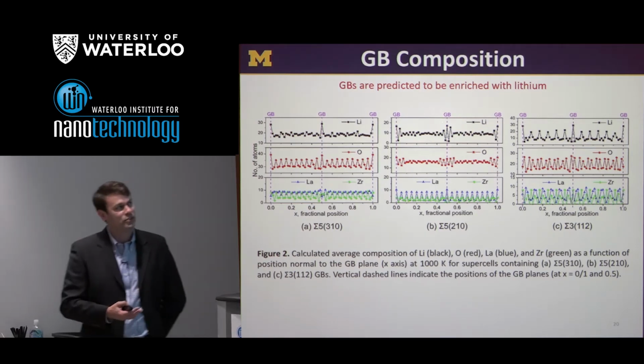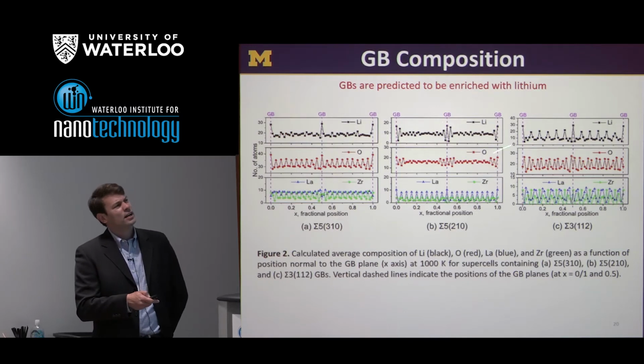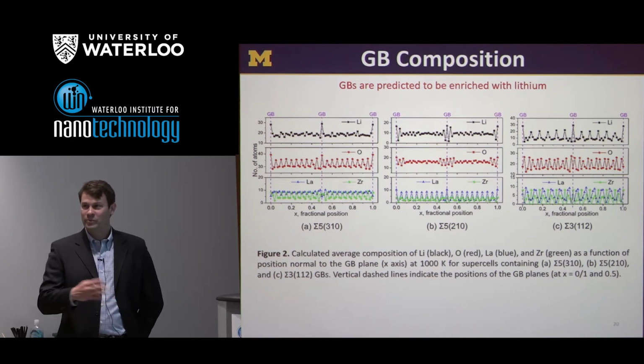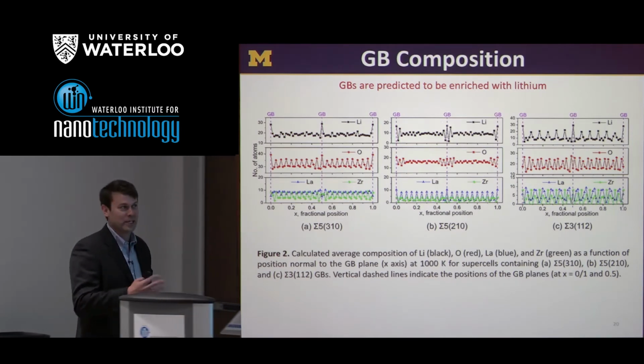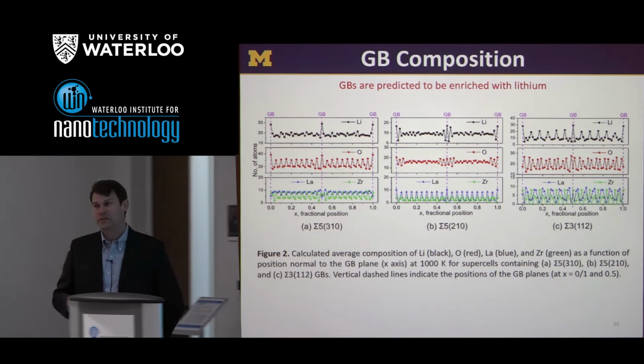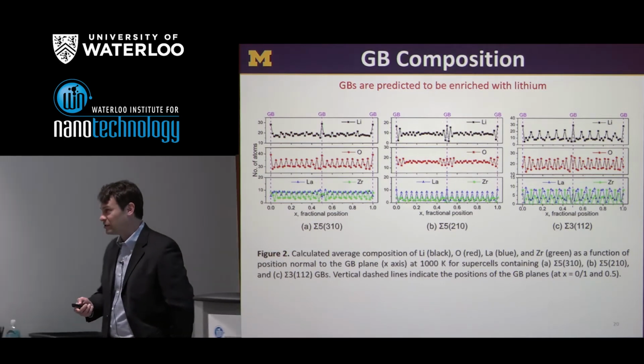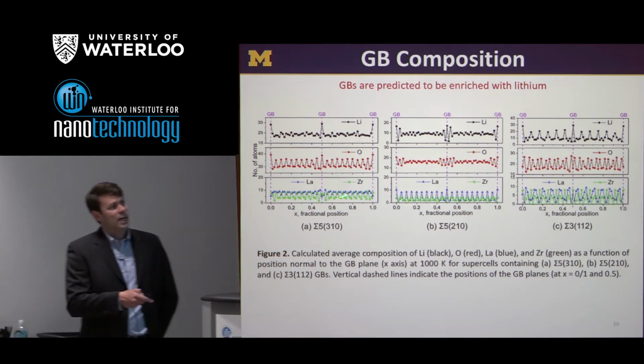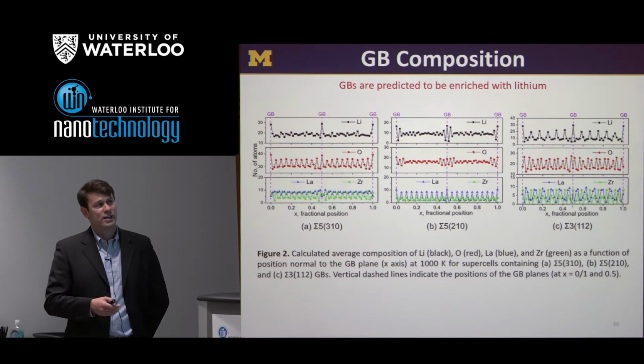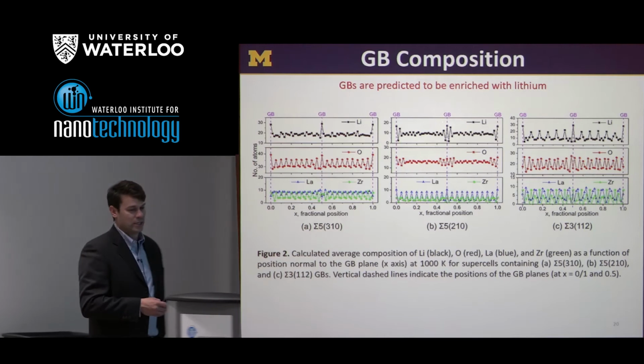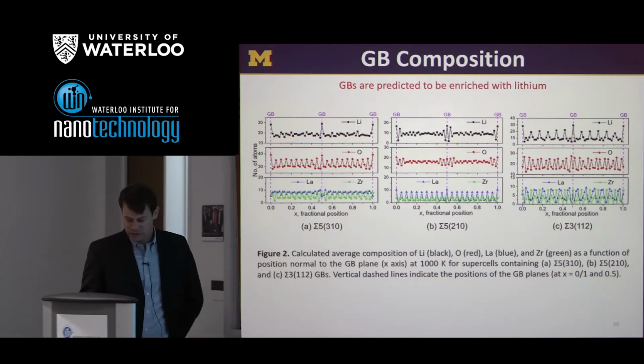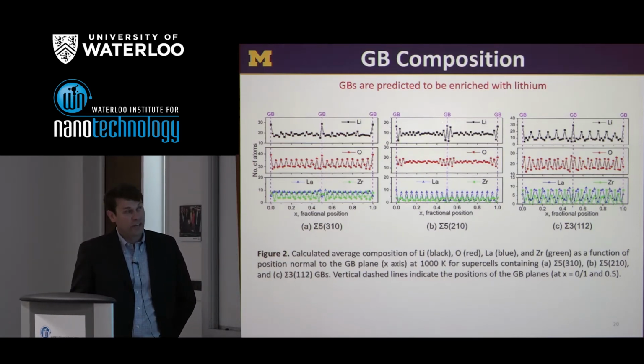So there's some enrichment of lithium occurring here, which also coincides with a somewhat weaker enrichment of oxygen. So perhaps there's some electroneutrality constraint here that we can't overload the grain boundary with positive lithium, but there has to be some anion present to balance that charge. But then for lanthanum, zirconium, there's really not much of a change in composition as we go across the cell. So maybe this grain boundary is enriched in, for example, lithium oxide.